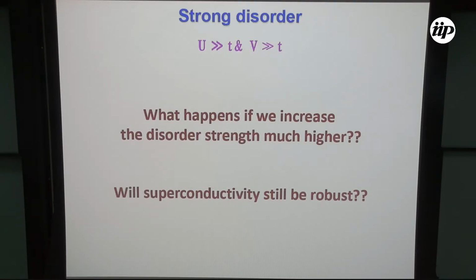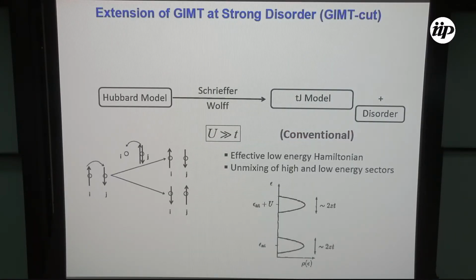So all is fine. We have immunity at weak to moderate disorder. Now, what happens if we increase the disorder strength? Let us increase it beyond the bandwidth, but not beyond U. So U is still the largest energy scale in the problem. We increase the disorder scale much greater than T. Should we expect the superconductivity to survive and be robust? To understand that, we should think about this transformation again.